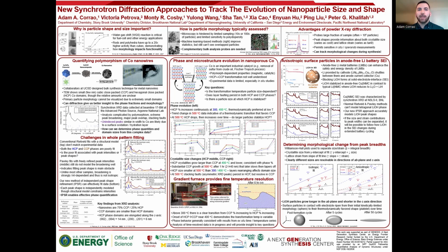In the last panel, we show the application of this independent peak shape refinement approach for following the evolution of particle anisotropy. Here, we used anisotropic fits to Williamson-Hall plots to deconvolute size and strain broadening and successfully determined particle shapes. The fitting approach used in these three cases is generalizable, and we're working to both build a more user-friendly interface and extend the models for routine use.